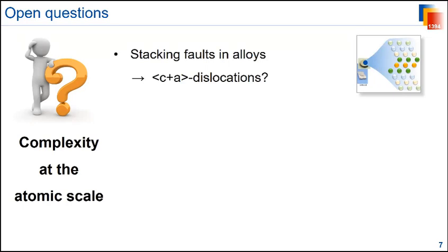The stacking fault energy on the basal plane is an indicator of what's going on, but it's not actually a mechanism, particularly not for flow off the basal plane. Because the macroscopic deformability that we saw here and the calculated stacking fault energy must be related via some sort of nucleation and stability of non-basal c+a dislocations. And how these come about, that's determined at the local atomic scale, but we don't know it yet.